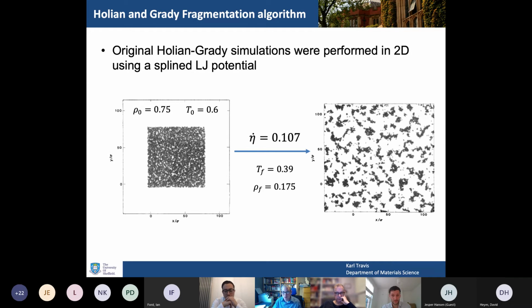And then what you do is you stop the simulation at some particular difference in box length or box area or volume, whatever you want to call it, and you examine the contents. So here what we find is the temperature's dropped to 0.39. Remember, it's adiabatic, and the density has now gone down to 0.175. In fact, you engineered it so it ends up at that density. And you can see that the liquid broke up into fragments of various sizes.